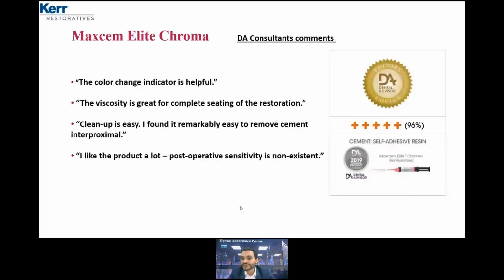And actually, in 2019, we got an award from Dental Advisor for Maxcem Elite Chroma. The clinical evaluation at that time was 96%. Here you can see an example of the evaluation of the consultants, the doctors. The color change indicator is helpful. As we mentioned, the color starts pink, and once the color fades and disappears, it means we are in the gel state. The viscosity is great for complete seating of the restoration. The cleanup is easy. Post-operative sensitivity almost nil. So you have a cement that is easy to apply, easy to handle, with a color indicator, easy to clean up, without post-operative sensitivity.